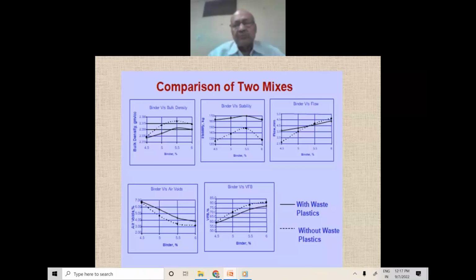Stability values are required to be corrected because the standard stability value is meant only for a specimen of 63.5 millimeter height. These are the correction factors. So all these steps are similar to the conventional Marshall method of mix design.